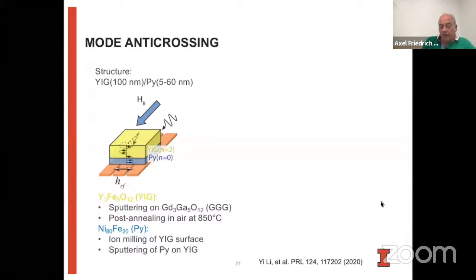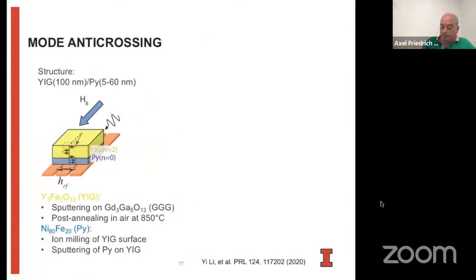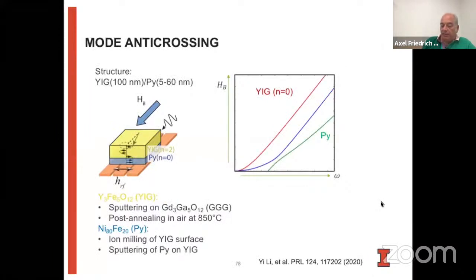Having said that, we grew a 100 nanometer thick YIG film with sputtering, and we grew permalloy films with different thicknesses on top of it. The yttrium iron garnet film was sputtered on gadolinium gallium garnet, actually at room temperature, and then we post-annealed it to crystallize the yttrium iron garnet and get a nice low damping film. After this process, we deposit the permalloy by first ion milling the yttrium iron garnet surface to get a fresh surface, so that we get a nice, strong interfacial coupling after sputtering the permalloy on top of the YIG. As I said, the goal is to see exactly something like this, where we have the fundamental mode of the YIG, the fundamental mode of the permalloy, and then the spin wave mode that becomes split right around this area here.